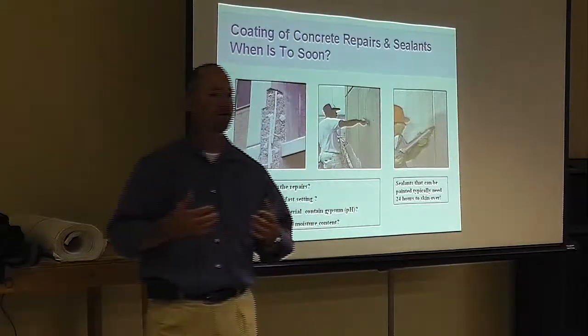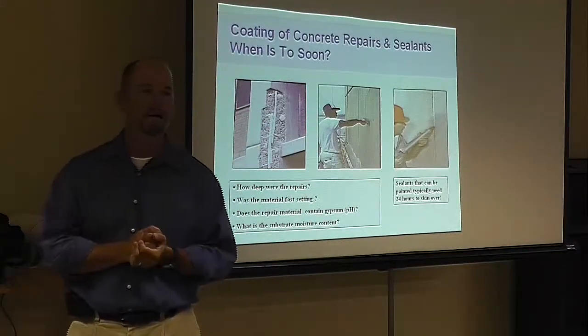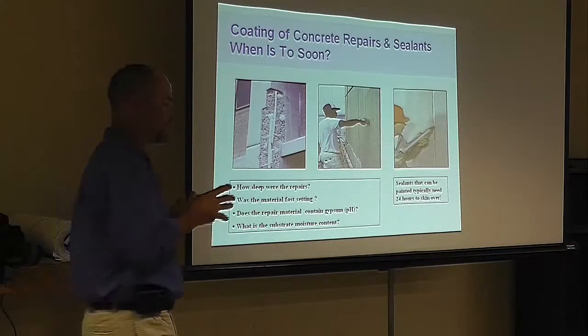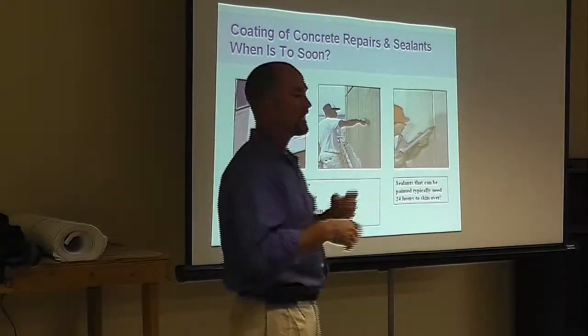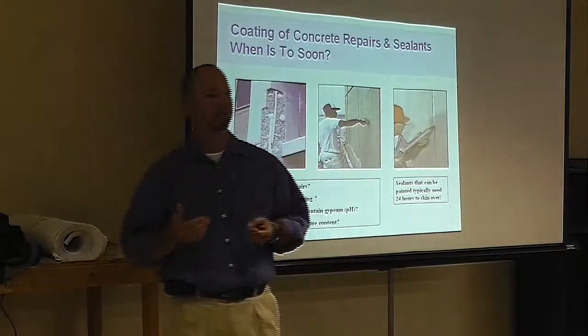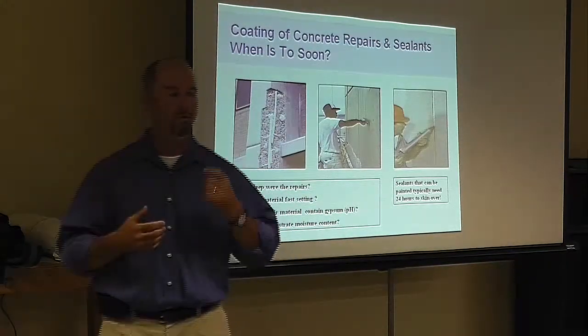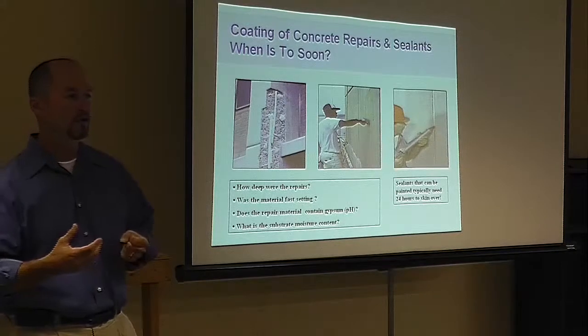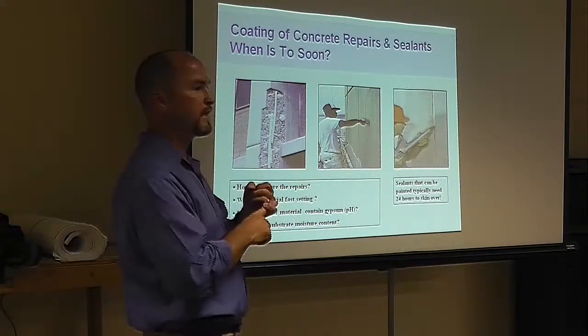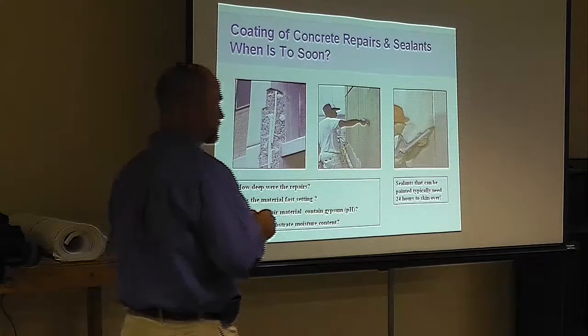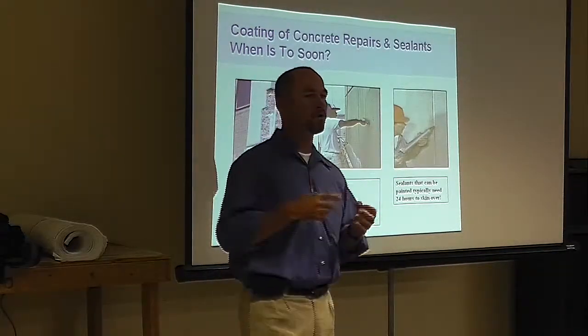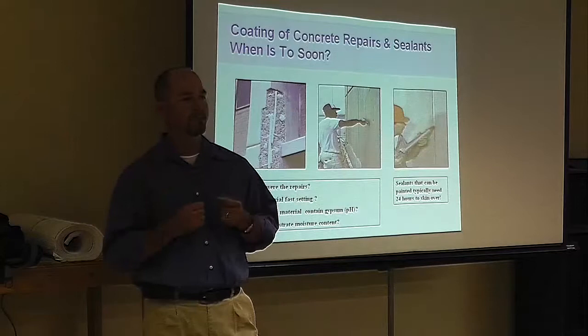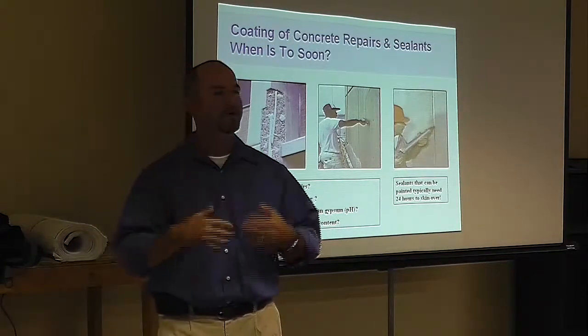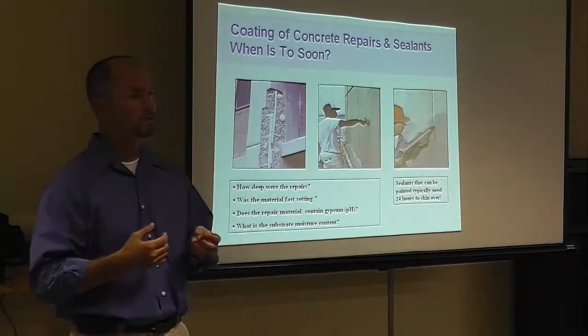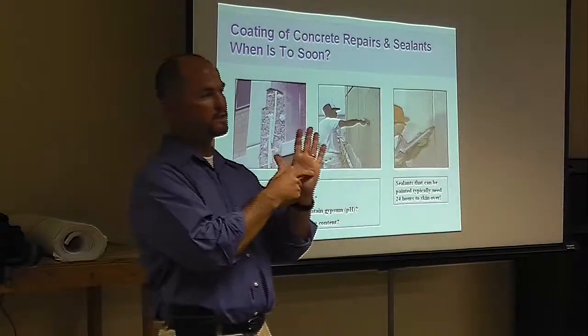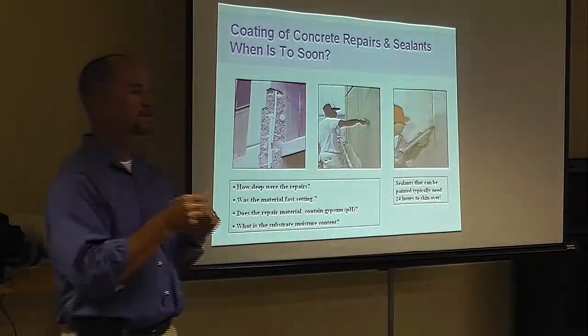I always get asked, I did the repairs, how quick can I throw the coating over the top of it? Well, there's one easy way to do it. You want the repair to have at least 80% of its strength before you coat over it. If it's a deep repair, three to four inches, it's going to take a little bit longer. And one thing you can do to bring down the pH on projects is vinegar. You can take vinegar and water, put that light acid on top, and it will bring down the pH of that patch so you can come back with a coating. High build coatings can usually handle pHs right around 12. There's an easy way to check with a pH pencil or litmus paper to show how hot that pH is.